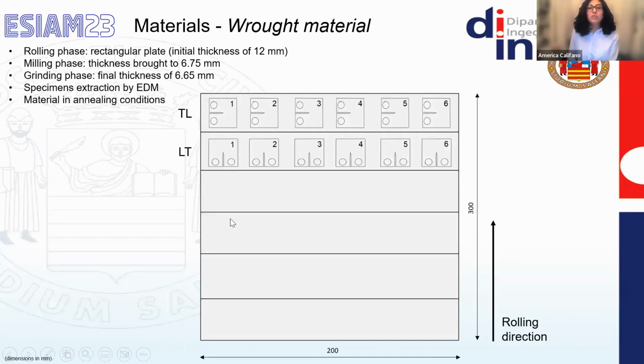On the other hand, considering the wrought material, at the end of the rolling phase, a rectangular plate was obtained with a thickness of 12 millimeters. It was milled and ground in order to obtain a final thickness of 6.65 millimeters as well. Here you can see a schematization of the plate from which 2 slices were cut out, and from each slice 6 specimens were extracted by means of the electric discharge machining method.